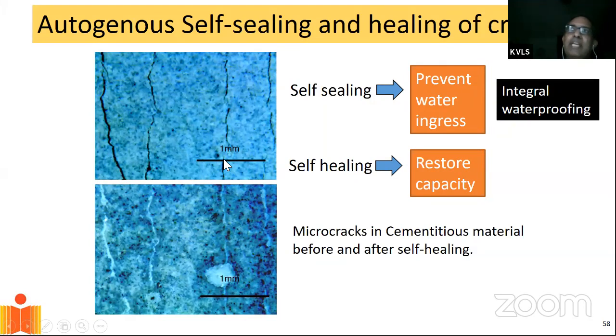So this is basically mimicking what the human body does. It's not just enough to seal the cracks, but then I should recover the original strength of concrete before the crack happened. So self-healing is now essentially talking about restoring the capacity of concrete after it has cracked. And this now is bringing in technology in the form of bacterial concrete, where we are mixing bacteria into concrete. And when the bacteria is exposed to atmosphere, it secretes calcium carbonate, which basically seals and heals the concrete. So this again is taking us into a domain where we're interfacing with biology and microbiologists in order to produce a viable solution that is workable in concrete.